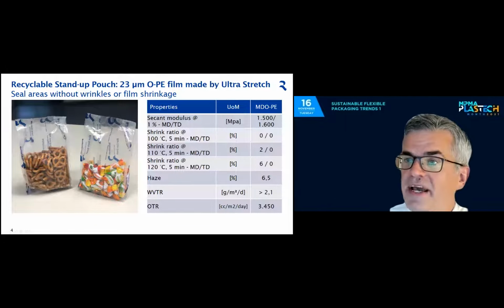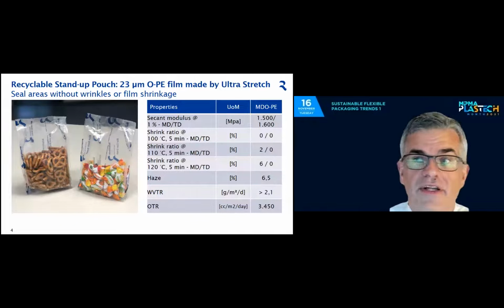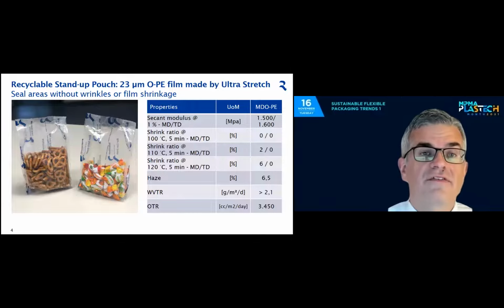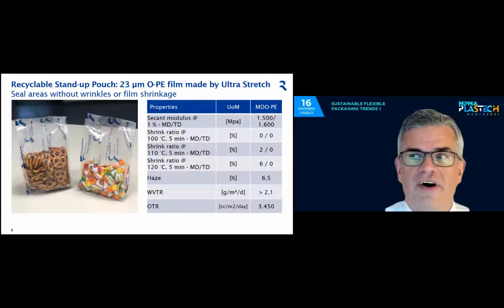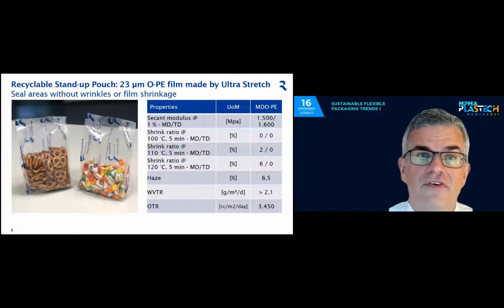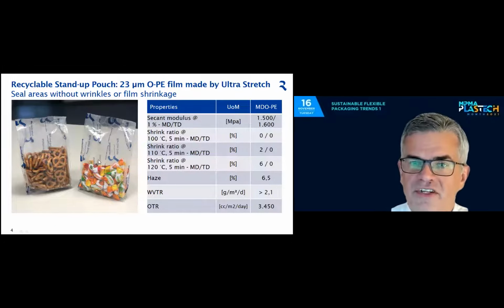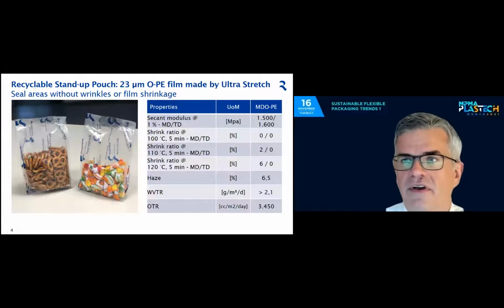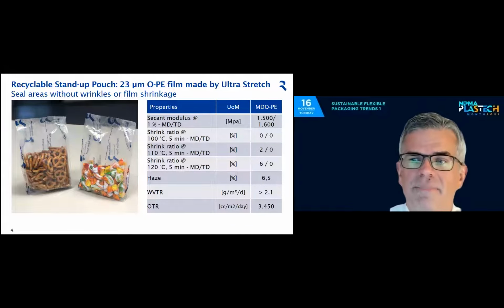which has very good mechanical properties. See the E modulus in transverse and machine direction of 1,500, 1,600. For sure, it's not as good as the E modulus, for example, for PET, which is well above 3,500 up to 4,500, but it's still good enough to meet the properties of such kind of pouches. The haze of the film is quite good. It's like a 6.5. So obviously a good and nice solution replacing PET.